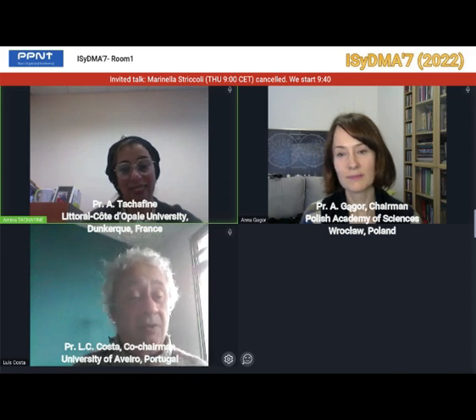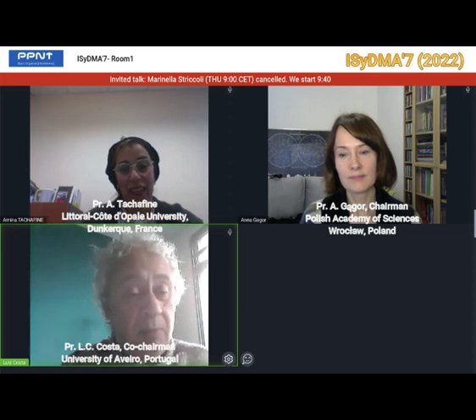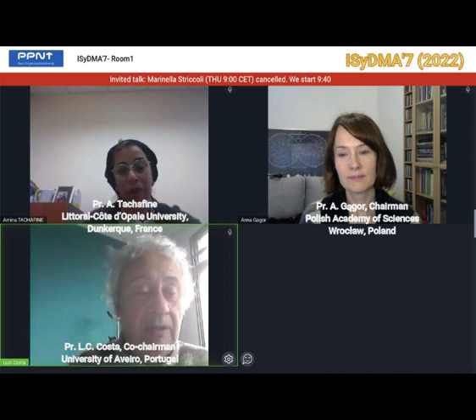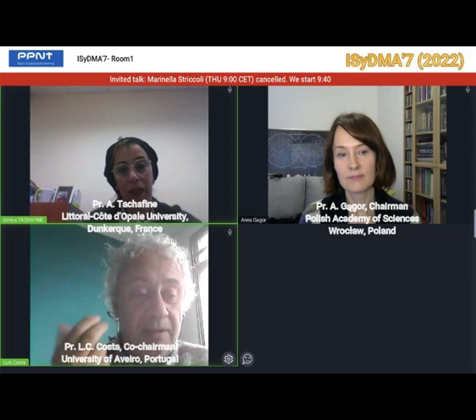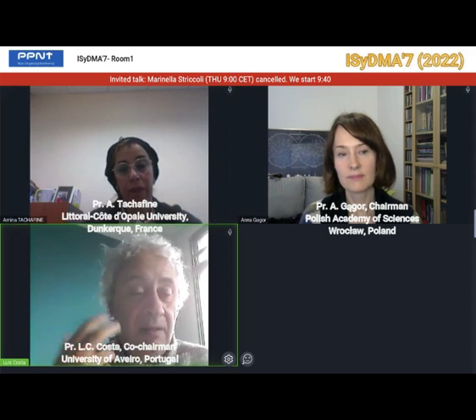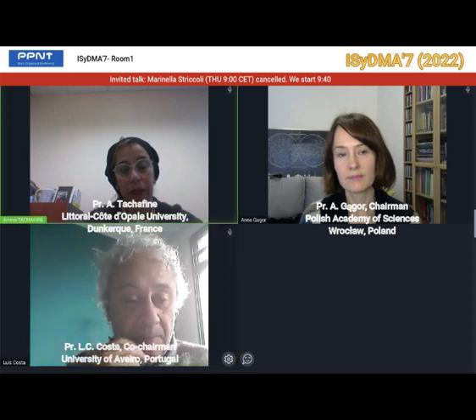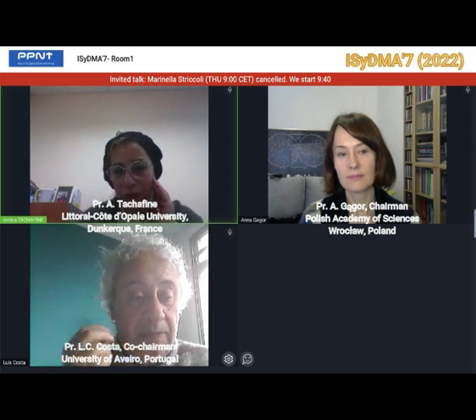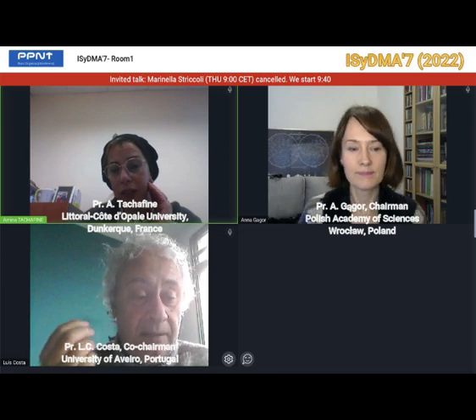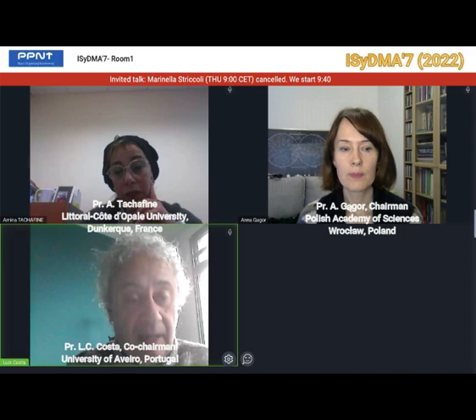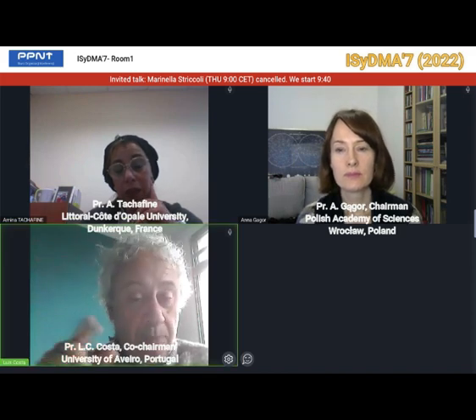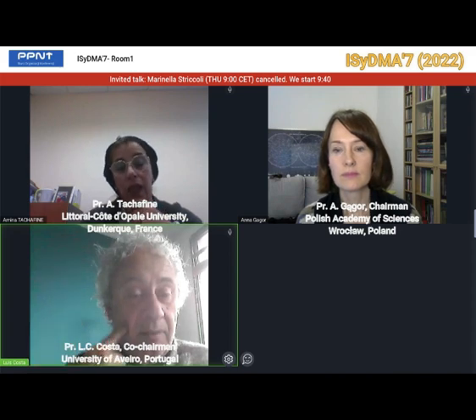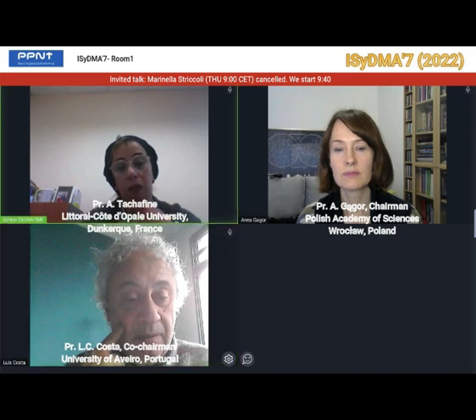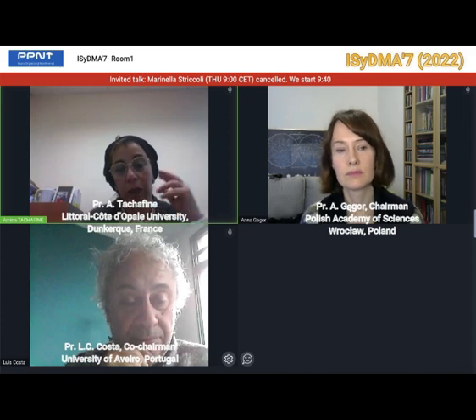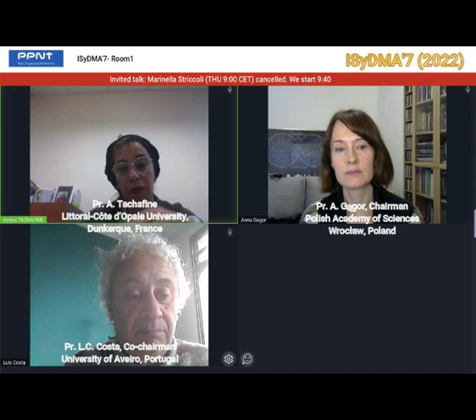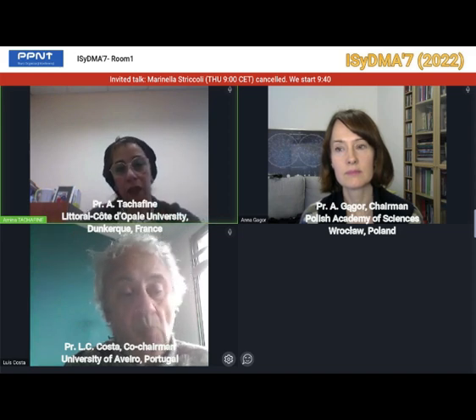Okay. It was interesting to see this calculus of n, this exponent that you use in the constant phase element. It is close to 1 in the grain, so that means that it's a Debye relaxation. Is this expected to you? It is normal because Debye relaxations are not so common in materials, and here we have a Debye relaxation for the grain because n, this exponent of the CPE element, is close to 1. Yes, it's close to 1. So grains are well crystallized, and in grain boundaries, n is far from 1 because of defects in grain boundaries.